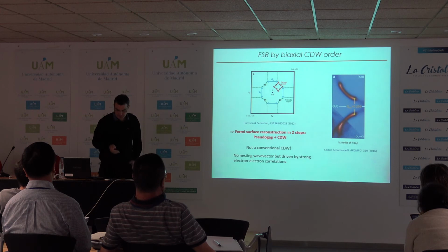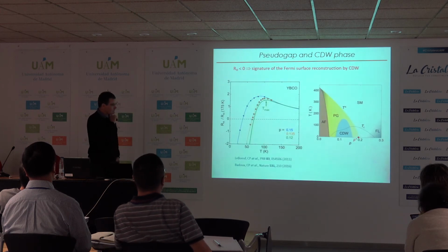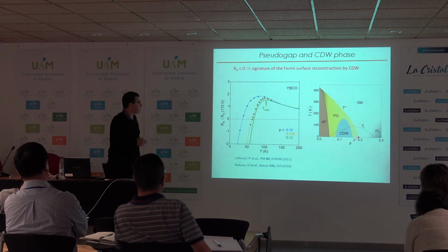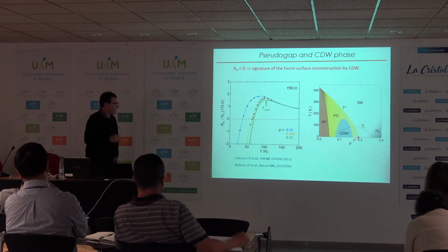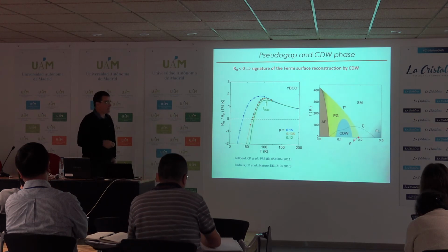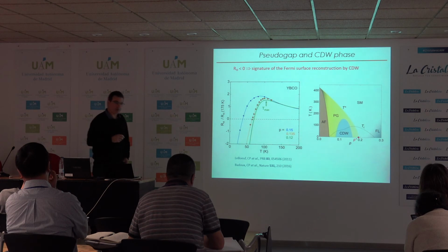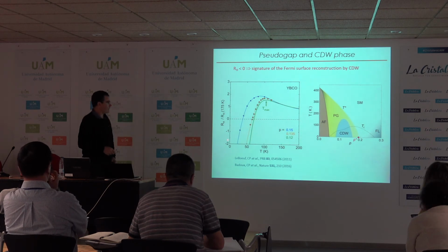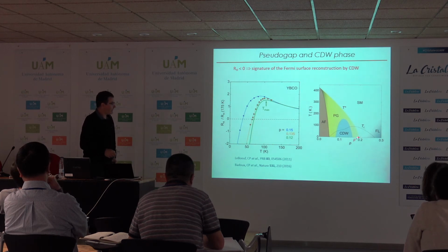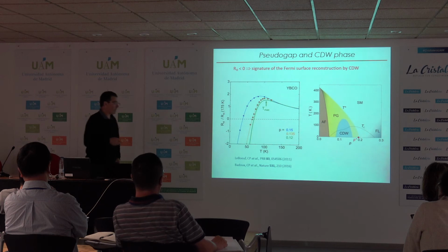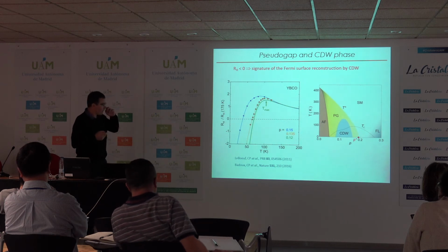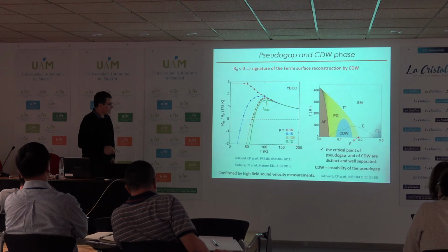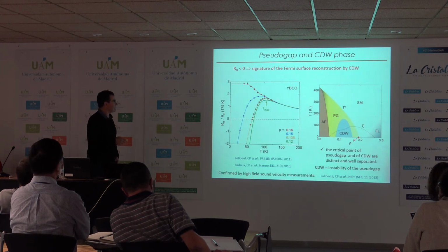Okay. Let me go now a bit further outside of this charge density wave. I would like to come back to Hall effect measurement. As I told you, the negative sign of the Hall effect is the signature of the Fermi surface reconstruction by the charge density wave. So here I show you again Hall coefficient versus temperature, measured of course at high magnetic field, at different doping levels inside the charge density wave phase. And the latest measurement that we have performed at much higher magnetic field, up to 88 Tesla, shows that at 16% now the Hall effect remains positive up to say 40 Kelvin.